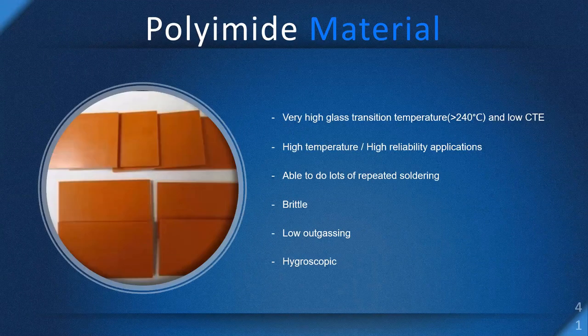Just a quick note on polyimide material. Polyimide is still the best material for high temperature applications. Actually, Isola just came out with a new benzoxazine based material that's second to polyimide, but very close. It actually has some benefits over polyimide. It's less brittle. It's good for filling thick copper. That's something I think we're going to see in automotive applications as that material becomes more commercially available. But polyimide is still used on downhole and aerospace and under hood, and it is a very good thermal material.